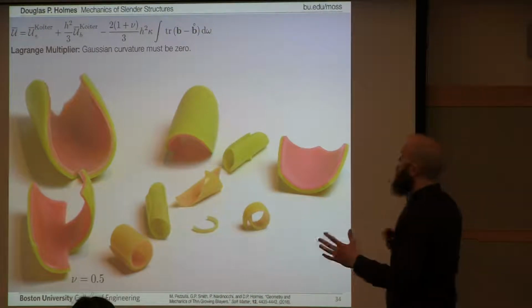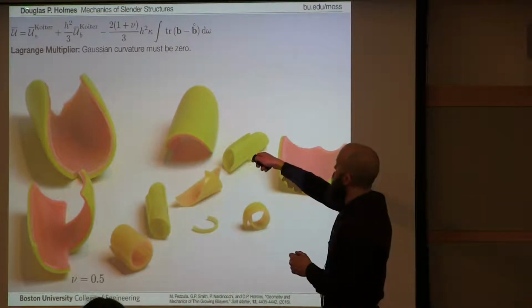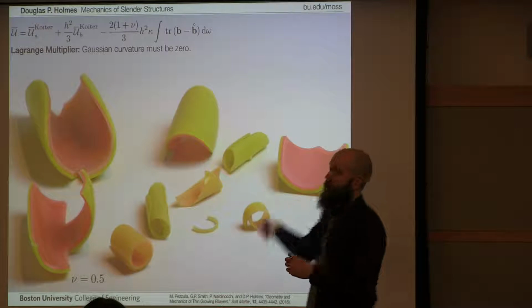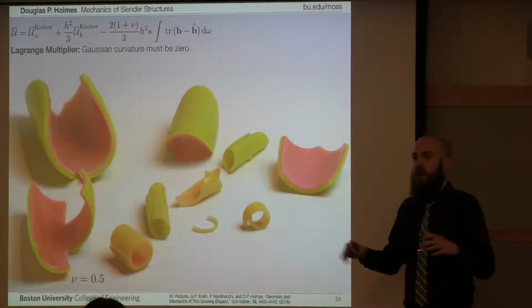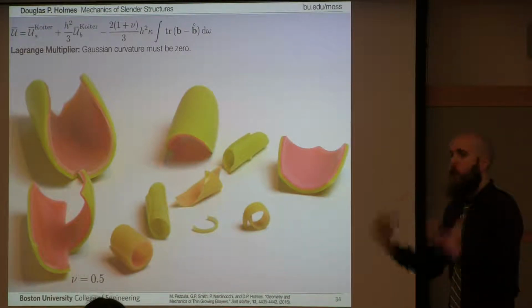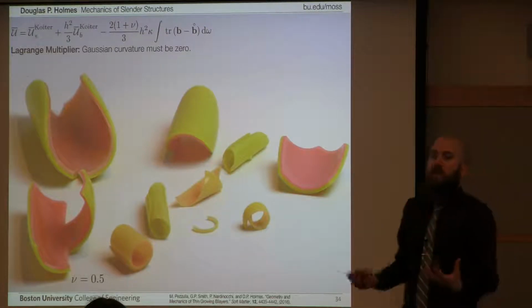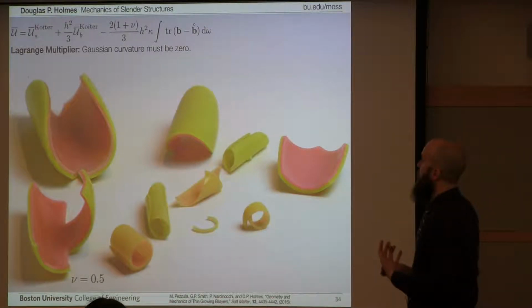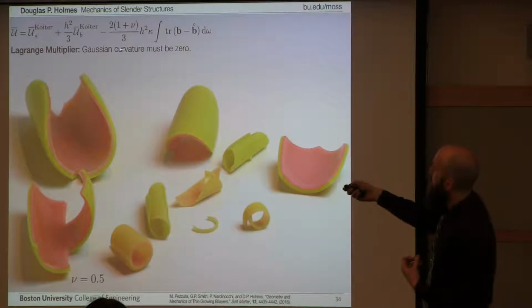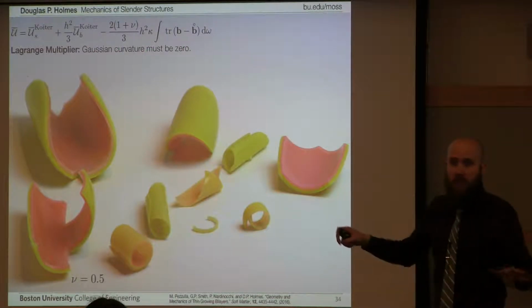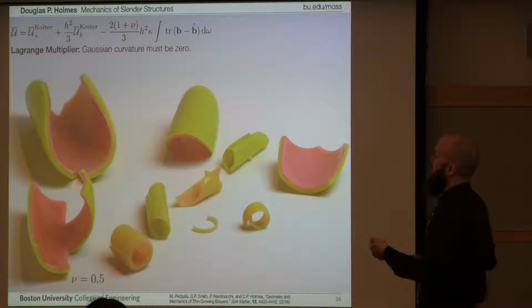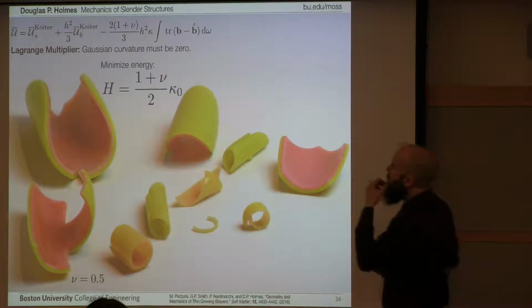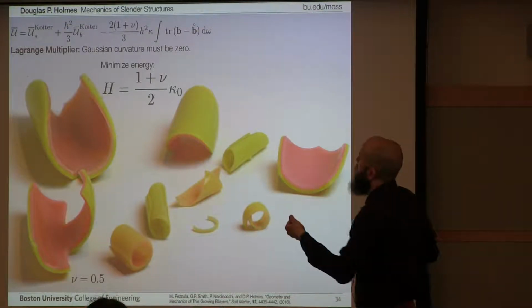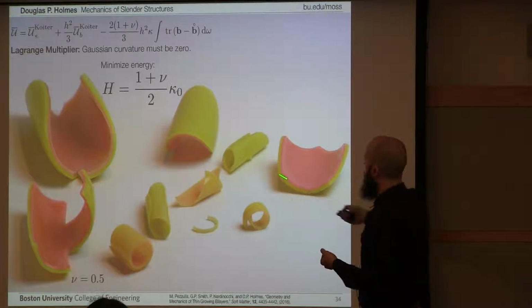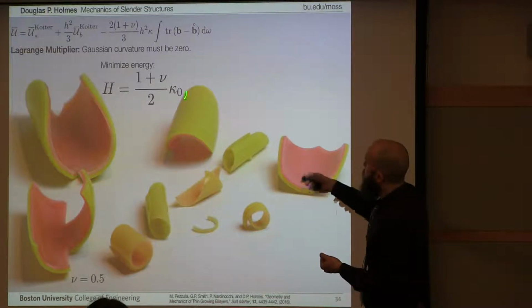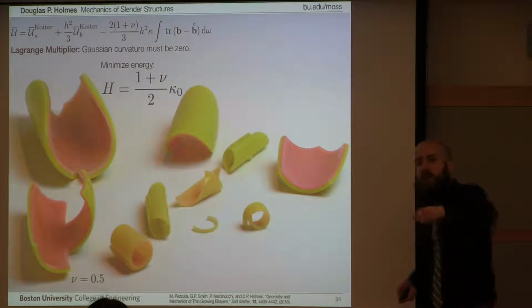And so we can solve this problem. We write down our energy that I showed you before with our potential. We say, we know that it can't stretch. And whenever you have a mechanics problem in which you know something needs to be constrained, you constrain that property with a Lagrange multiplier. So we take this energy, we constrain the Gaussian curvature not to change, and we minimize the energy. And what we find is, if you minimize this energy, you get an analytical expression for the mean curvature of this cylinder as a function of the natural curvature, kind of whatever the stimulus is doing.